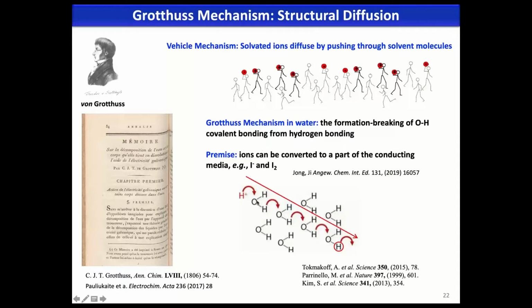Grotthuss's mechanism is different. You have the proton coming in, it's going to knock on the door of this chain of water molecules, and you're going to have hydrogen bonding formed, and this covalent OH bond will break, and this is going to be a domino effect. You're going to have this hydrogen released, forming hydrogen bonding with this oxygen, and so on and so forth. Eventually, this hydrogen will be stuck with this water, and this hydrogen will be released at the other end of the chain, right? That's the beauty of Grotthuss's mechanism. You don't have to transfer your ions. It's diffusion free. You can just have cooperative vibrations of different hydrogen bonding and covalent bonding. Then there you go. The ions will be transferred from the other end. Now, the premise of this transfer is you need to have a strong enough secondary bond. Hydrogen bond qualifies that, right?